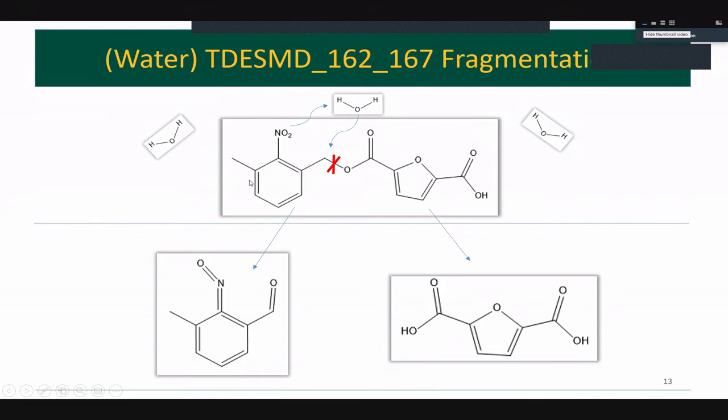An oxygen in the nitro group had decomposed and actually gone back and interacted with the hydrogens that were available in our simulation. So it was left with the nitroso group, which is part of the benzene unit you see below. Now this was for the interaction within water.